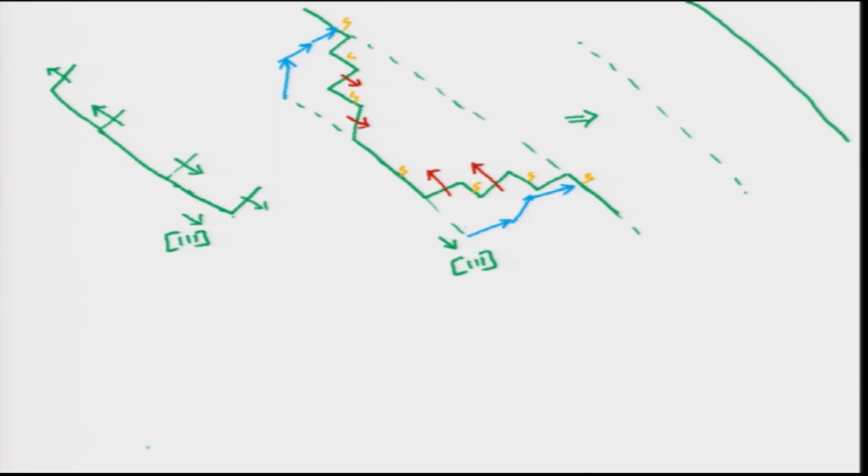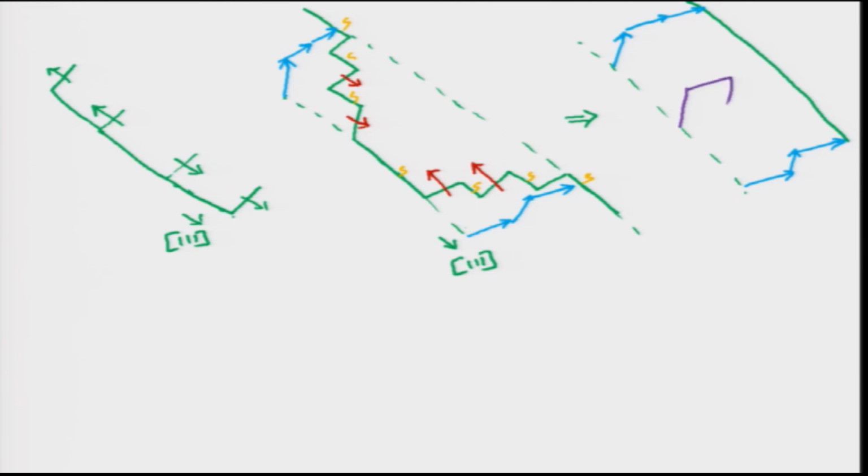Okay, it moved, like I said, part of it moved through one direction, the other part moved through the other direction, but eventually they are all now on one plane or along one line. And in the process, these parts which we saw over here have now moved together to form a loop, and these are all non-screw dislocations, meaning a prismatic loop.